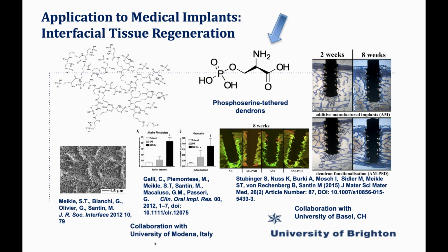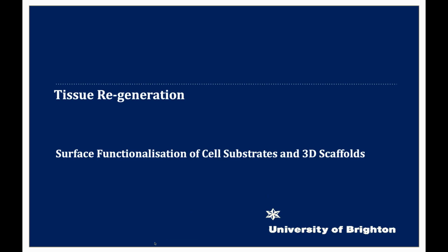We have demonstrated that this molecule can indeed be efficiently grafted on the surface of the biomaterial to the hyperbranched molecules to induce a fast mineralization of titanium, to induce a differentiation of progenitor cells adhering on this surface into bone cells, osteoblasts, and in vivo to lead to the formation of a tight network of the bone trabeculae, which is a clear indication of the bone activity.